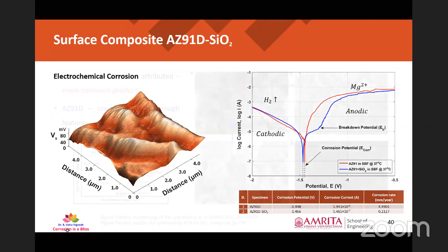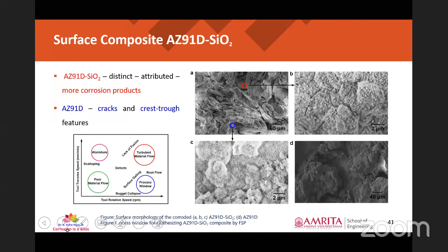So when we observed the same surface under scanning electron microscope, we observed unique features in the corroded regions. We could literally see the formation of star-shaped cluster products, which is also a corrosion product, and bubble-shaped corrosion products in this scanning electron microscopy. Those are all attributed to the formation of corrosion products within the corroded surface. That has limited the corrosion rate of the materials with respect to the increase in immersion period.